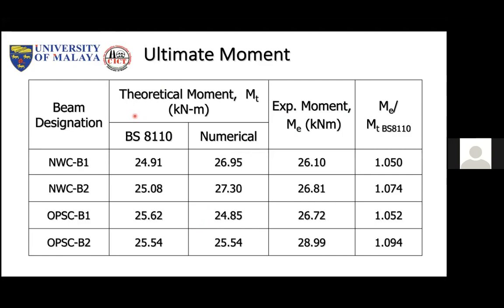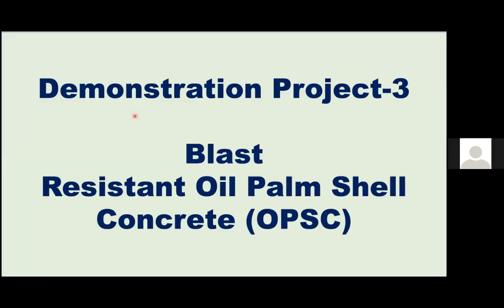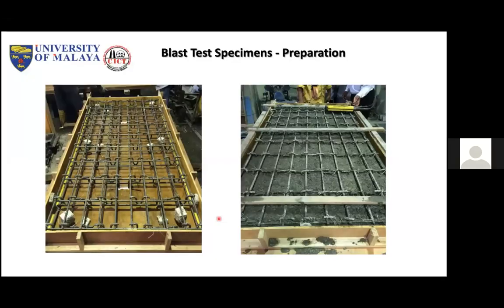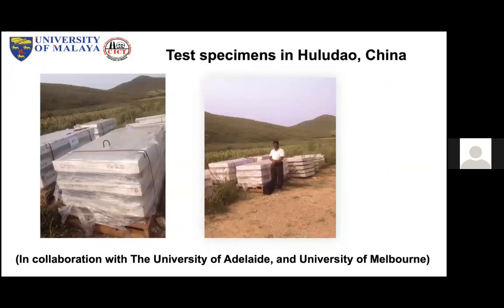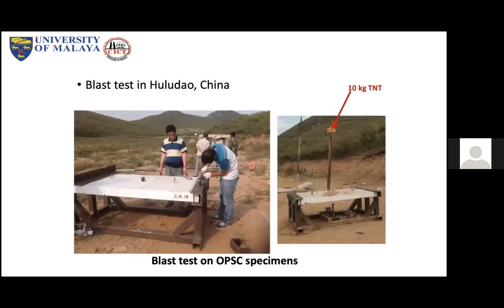So we compared with the different codes of practice, and we used that for our next project. This project is very interesting, where we developed a blast resistant concrete using that. We manufactured slabs of 1 meter by 2 meter, with 150 mm and 120 mm slab thickness, and we sent them to the testing site in another country, China. We have our collaborator from the University of Adelaide, and they had a facility. So we sent our slabs there, and we tried to test them using 10 kg TNT.